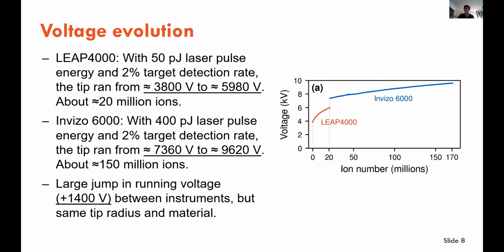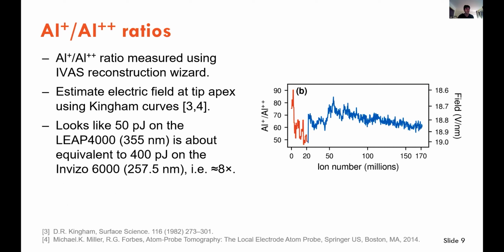It's pretty cool. So despite the large change in voltage, there's not a significant change in the aluminium plus double plus charge state ratio. So we can estimate the field using Kingham curves, and it all comes out being kind of roughly the same. The charge state ratio is about 75, the field's about 18.5 to 19. Basically, the shorter laser wavelength, the dual lasers, the nominal laser pulse energy, about 8 times higher on the 6000 to what we'd use on our LEAP 4000.